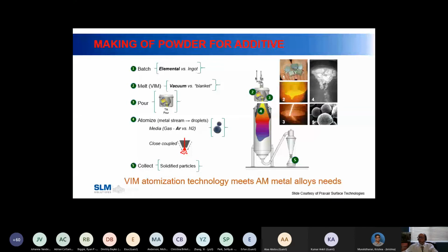And once it's melted, you can see these steel lines going into the top. They will open the port at the bottom and put a few hundred pounds of argon, could be nitrogen, but in 90% of the cases, it's argon. And they will push that molten metal through that orifice, through that gate. Now, around that gate are high-speed streams of argon. And when that liquid metal hits this, it will come in contact with those high streams of argon, and it essentially atomizes all of the molten metal. And that's reflected here in this picture titled number 4.